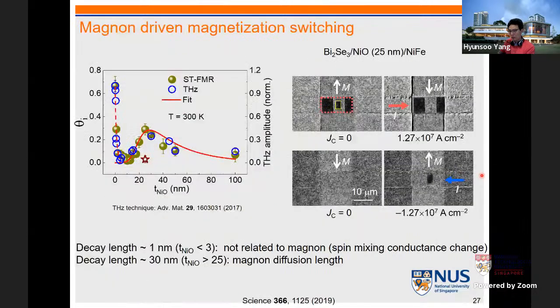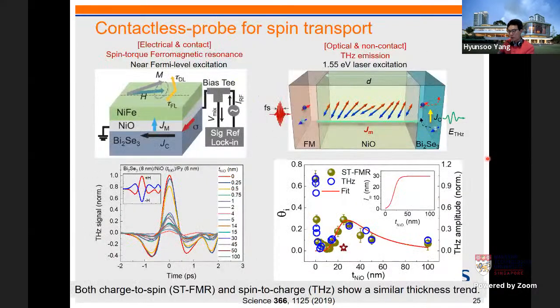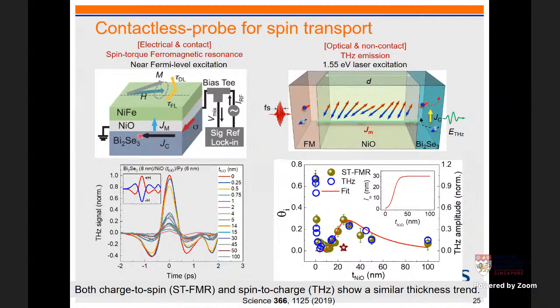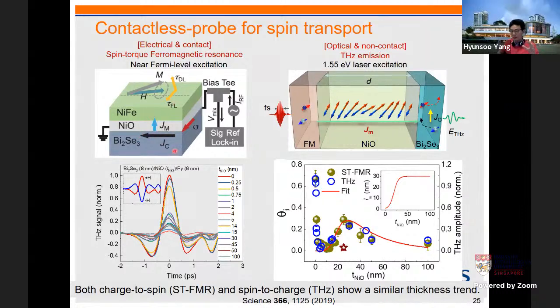Actually, what we are trying to demonstrate is a pure current-driven phenomenon. If you look at this experiment, we just apply current and then we can switch this magnet from one direction to the other. In this case, there is no laser involved. The laser experiment we just use to show the inverse process and to confirm our forward efficiency. When I talk about the forward efficiency, we inject charge current, convert to spin current and switch. To confirm whether this trend is correct, we use the opposite process. This is an inverse process, meaning we generate spin current and then convert to charge current. So this is spin to charge conversion. The previous spin-torque ferromagnetic resonance measurements and even switching measurements are all charge to spin conversion processes.